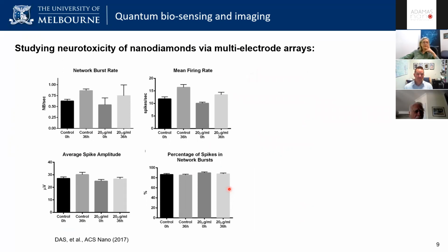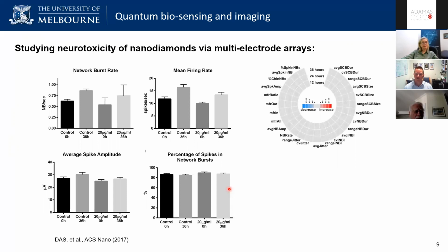Now, what was fantastic to see was that there was no statistically significant difference between the electrical activity of the neuronal network before and after the addition of nanodiamonds. And this was a real surprise, even to Steve Petru, who's done a lot of work in this area. He hasn't seen a material with this kind of limited impact on the electrical dynamics of neuronal networks before.